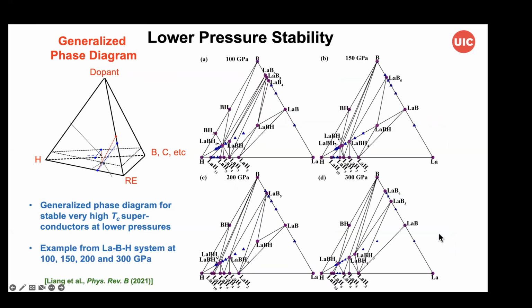So just on the one point regarding looking at compositional effects and looking at stoichiometric compounds, a lot of work has been done by Lilia's group and others looking at stoichiometric compounds that are stable at lower pressure while preserving very high TC, for example, in the lanthanum boron hydrogen system. And this is work that we've done as well in collaboration with several groups.